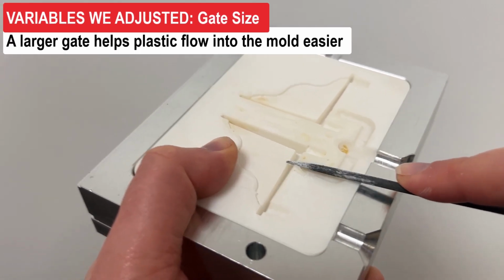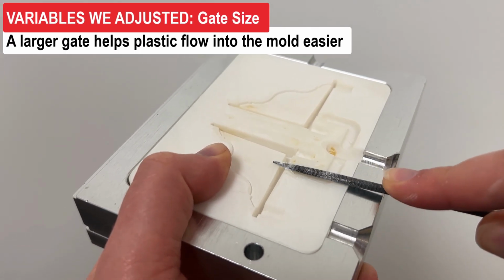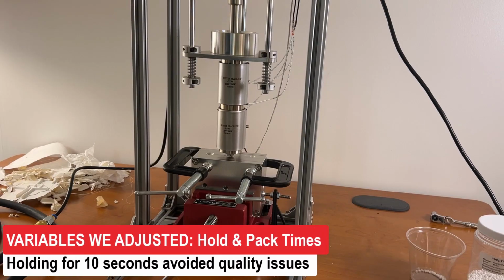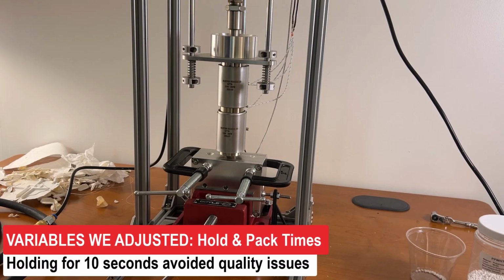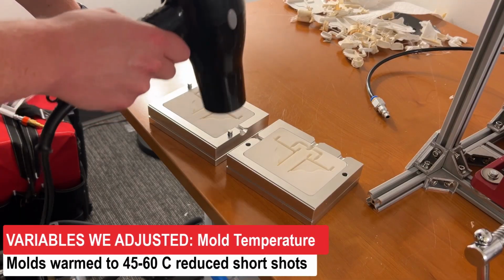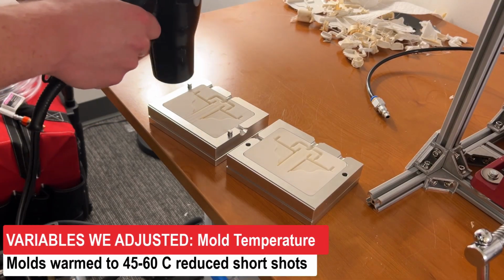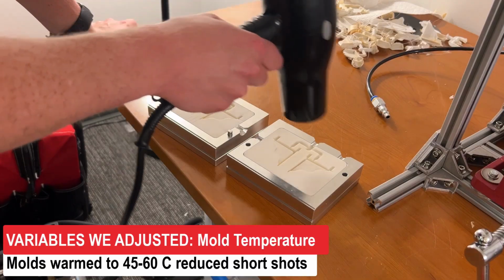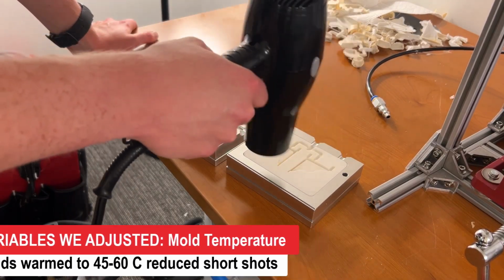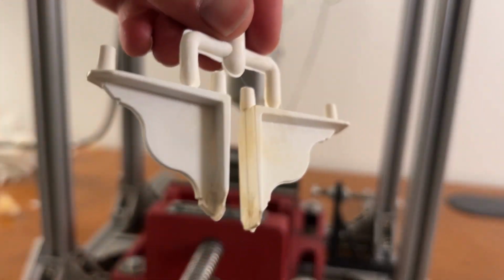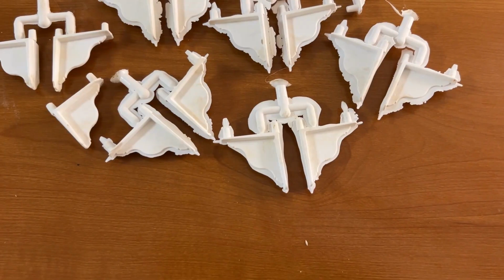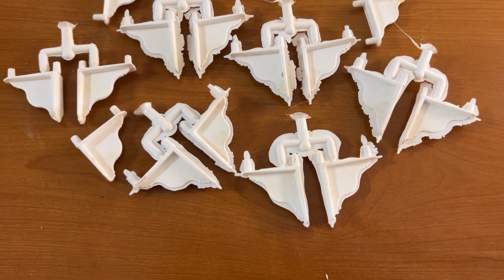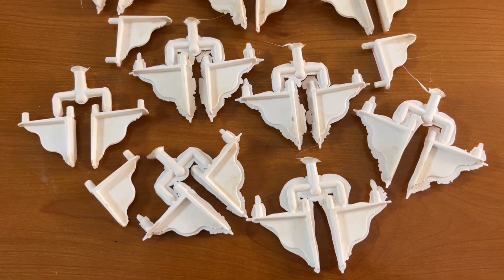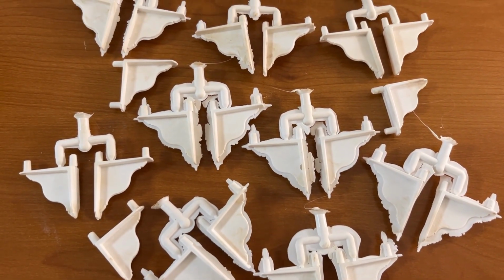Increasing the size of the gate, which we did with this round conical file, changing the hold and pack times. For this mold, a hold of about 10 seconds worked best, as well as heating up the mold prior to injecting using a blow dryer, which definitely helped reduce short shots substantially. Once we got it dialed in for this part, we did get plenty of good shots, which was a huge win. Still, some flashing was present, but if we had a milling machine, we could get this perfectly flat, and that would help immensely to reduce flashing.